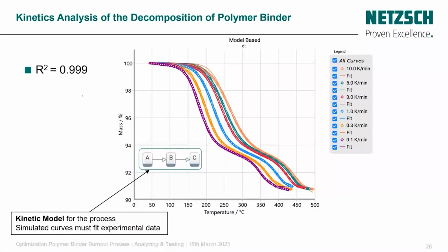So after measuring different heating rates and determining the number of steps, now we come to the stage of the kinetics analysis. And as you can see, we describe our experimental data by a 2-step reaction, where A goes to B and B goes to C as a consecutive reaction. And in this case, the simulated curves must fit the experimental data. And we can say that the simulation data are in good agreement with the experiment, because we have the R-square, or the coefficient of determination, which shows us the goodness of the fit, equal to 0.999.